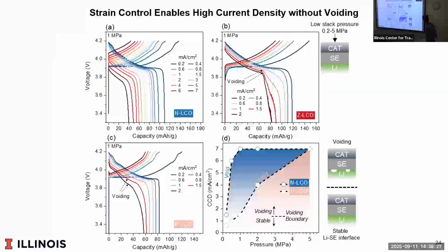And a big problem is you actually get voids. And you get a void here if the material's trying to expand. And so you can make it so that basically there's just enough pressure that you don't get void formation. We can go over the details later, but these are just a bunch of charge and discharge at different currents. And this is a map that basically, if you do it right, you can go all the way up to here. You can go to 7 milliamps per unit area, where if you do it wrong, you're much lower. You're only 4 or 2, depending on the orientation.